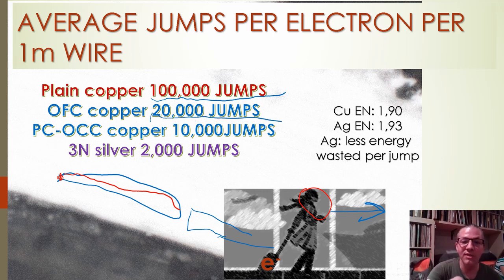Ohno continuous cast copper, this is the one that they use in cartridges. So for example, Audio-Technica uses it in their mid to high level cartridges, but every cartridge manufacturer nowadays who builds decent mid to high class cables, they use Ohno continuous cast copper wire. It only takes 10,000 jumps because this is the one that has the 100 micrometer crystal size, and silver just takes 2,000 jumps, which is 50 times less smearing and rectification effect than plain copper.